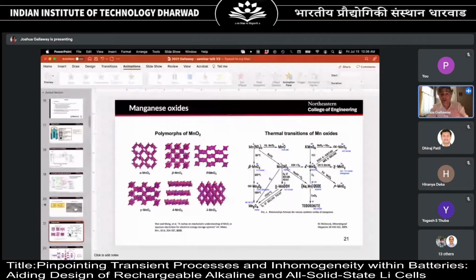And you see these have different arrangements. Now, the alpha form has these holes in it, and as a battery material, it works because you put ions into those holes. This delta MnO2 down here has layers. They're sort of holes that are very, very long, and ions go into these layers. That's how cathode battery materials typically work. So when we make MnO2 rechargeable, our batteries cycle as this layered type delta MnO2.